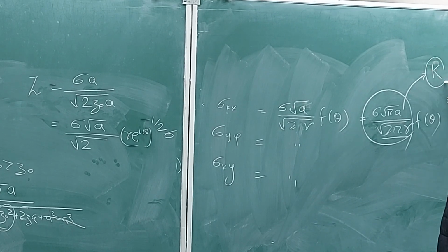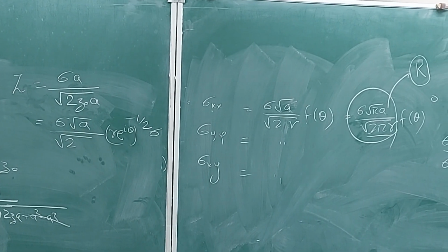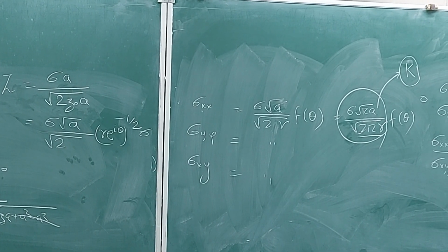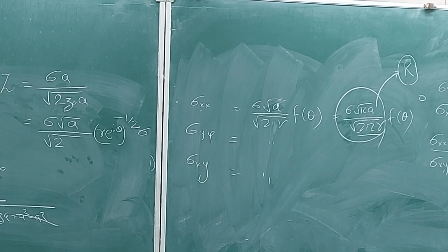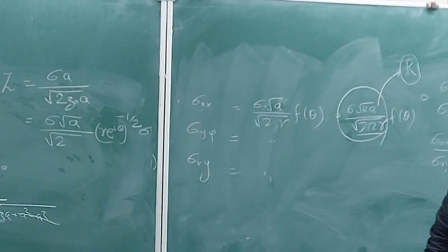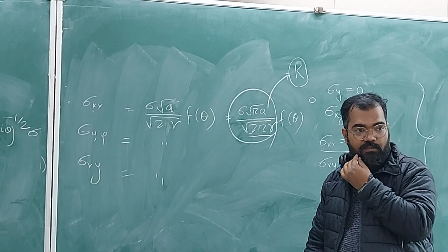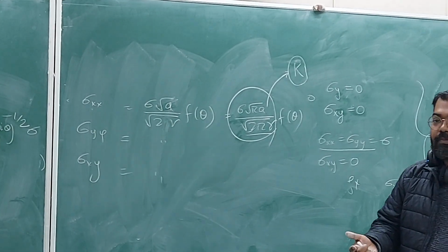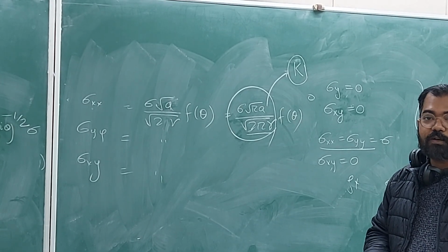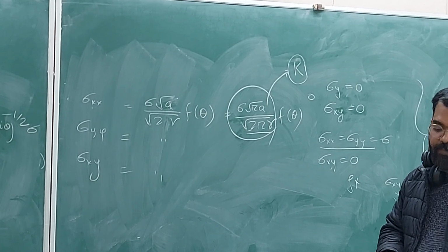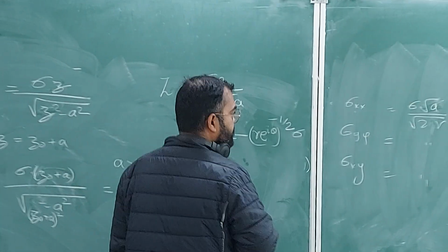This is described by the symbol K, and called stress intensity factor, and this is credited to George Irwin. And there is a group of fracture mechanics people who believe that there was no need of pi. Appears to be true. And they say that if you didn't have pi, even then the whole of fracture mechanics would have been the same. It's a constant value, so there was no need of it. But because Irwin did it in this way, people have been using it.